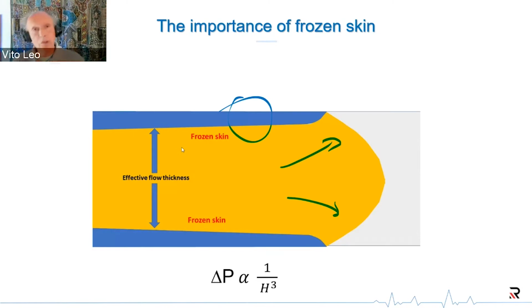First of all, it's not going to be the same everywhere throughout your cavity. And of course, it will vary also over time. It is, of course, extremely sensitive to mold temperature because that is the dominant boundary condition to be taken into account. But it's also extremely dependent on the injection speed. Because obviously, if you fill your cavity in a fraction of a second, you literally have no time to move the heat from the plastic to the steel, which means that you will not have time to grow much of a frozen skin. So it's a very dynamic problem.